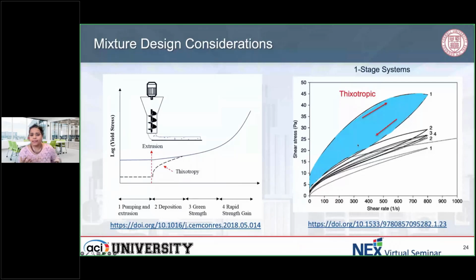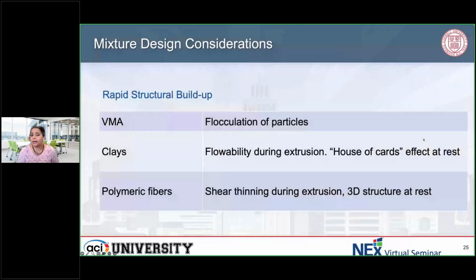To get this really fast structural buildup, there are systems that we could use. For example, VMA is a viscosity modifying admixture. We already use them in concrete, specifically, let's say, self-consolidating concrete, where you have flocculation of particles, which really helps with building up that structure. You could also use clays, which are typically flowable during extrusion. But once they're at rest, they have that house of cards effect, where they have a specific structure to them. Then during that deposition, you get this increase in yield stress that we are looking for. You could also use polymeric fibers that could create this 3D structure at rest.